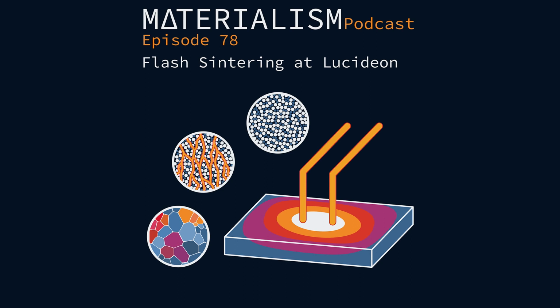Also, you do mention whether it's limited in geometry. We have developed a contactless system where we are igniting a plasma and rastering that plasma. If you imagine a taser, you've got that kind of spark between two electrodes. We're trying to ignite a plasma at a low furnace temperature and raster that across the surface. So you could think about using that for thin layer ceramics and coatings, environmental barrier coatings and things like that. So there's two arms to our flash sintering: the contact and the contactless, with different applications that we're trying to scale up.